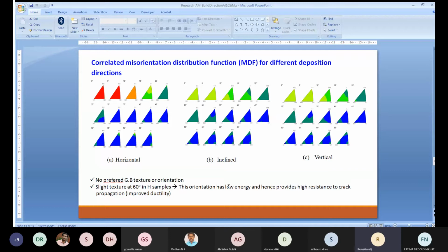And we have also gathered the data from the XRD and made the misorientation distribution function. We call it MDF for different deposition directions. From this figure, what you can understand is that in the vertical and horizontal directions, there is a preferred orientation, a slight texture at the 60-degree angle. This is useful because this orientation has low energy, which helps provide high crack propagation resistance. In other words, because you have high crack propagation resistance, you have improved ductility. And we did not find any preferred grain boundary texture or orientation from the MDF.